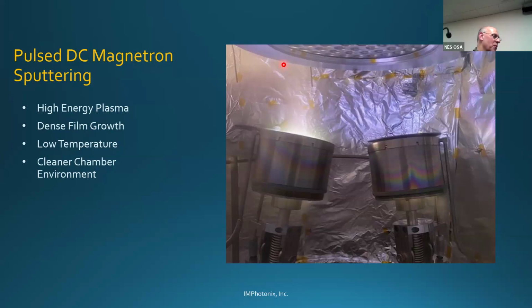So when we do physical vapor deposition, we use SiO2, and whether it's tantalum pentoxide or titanium, those are compensating stress films. One is compressive, the other is tensile. I'm assuming we haven't had that problem because our coatings go up to about 50 layers, so we don't see big issues with stress.